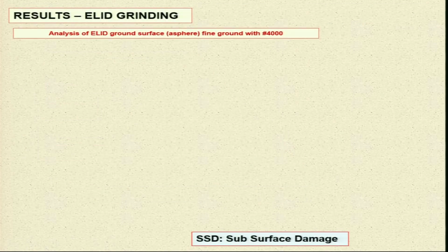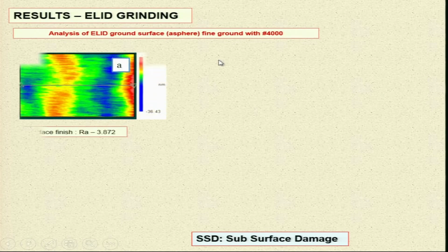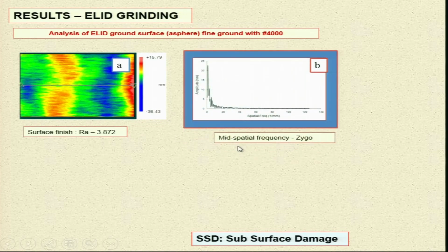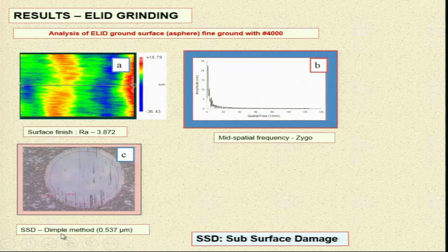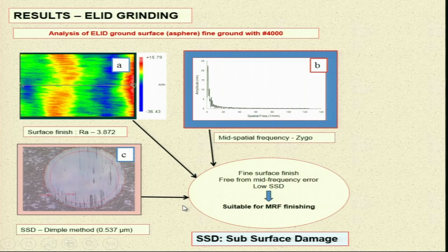Results of ELID grinding: analysis of an ELID ground surface, an asphere surface, fine ground with 4000 number grits. You can see here the surface finish Ra, and the mid spatial frequency that you can see here. This is the graph given over here, and this is the subsurface damage measured by the dimple method that you can see here. So, a fine surface finish free from mid frequency error, low subsurface damage that you can see over here, and it is suitable for MRF finishing. Means after obtaining the ELID surface of this nature, you can go for the MRF, magnetorheological finishing process.